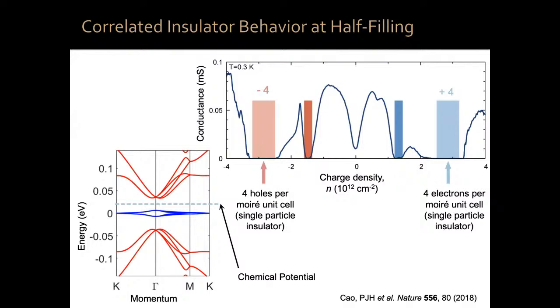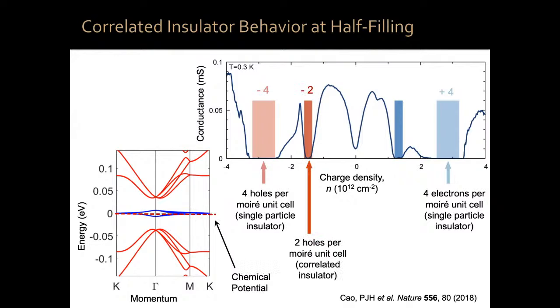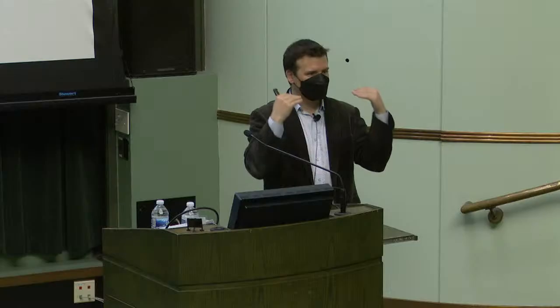The interesting thing that happens is if I add 2 holes per Moire unit cell, my chemical potential is in the middle of a band. I have plenty of electronic states there. This should be a very good metal. However, my conductivity, my conductance is 0. Yeah? This is something very unusual that doesn't happen in single particle physics. And this insulator state is a correlated insulator state. It's an insulating state due to interactions between our electrons.